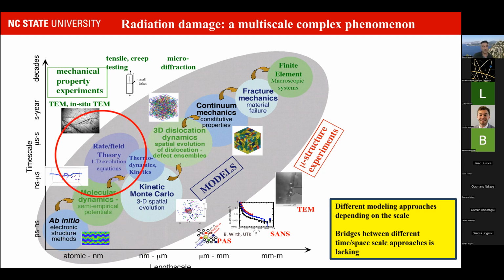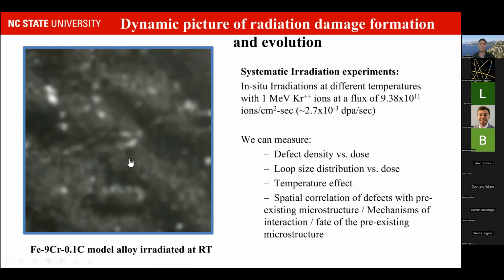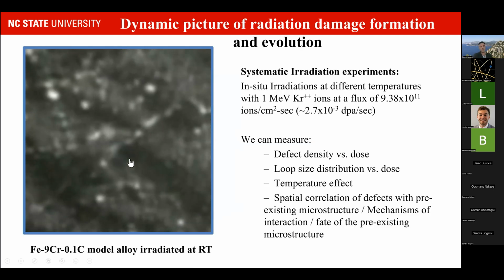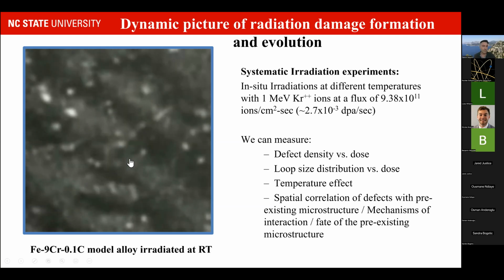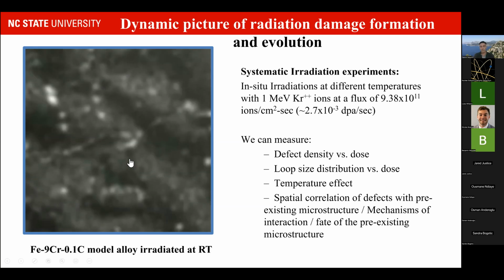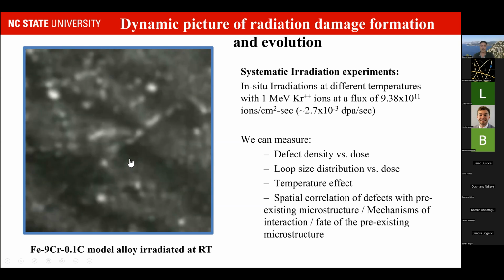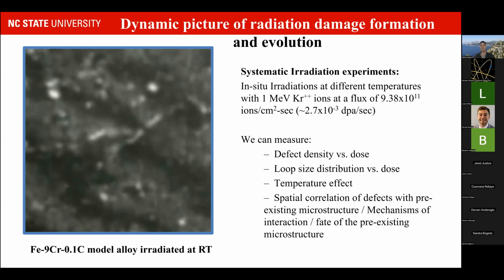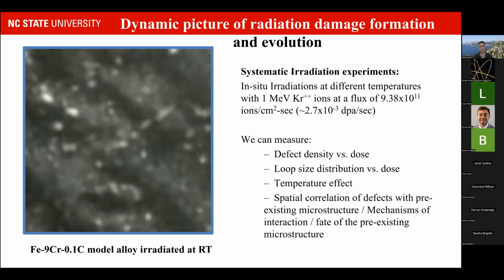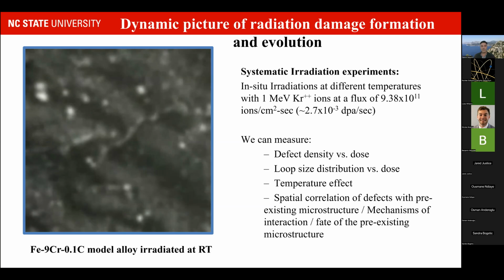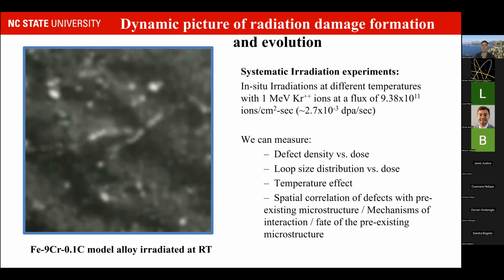For that matter, this is where we sit in terms of in situ TEM and TEM analysis of radiation damage. It's basically in the mesoscale, as I mentioned earlier, and it's to benchmark models that are based on rate theory. So what do we see? I'm showing you a little video that we recorded for a model martensitic alloy. The beauty of the technique is that we can record videos as we wish, and we see here in this dark field some white features, white dots, that are basically clusters of point defects and loops. They could be interstitials or vacancies; you can't tell just by looking at the contrast. But the bottom line is that these videos show how dynamic the process of radiation damage is.